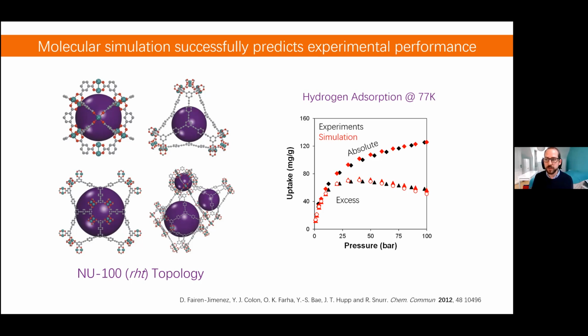Sometimes when we have such good simulations, we say, well, be careful. Did we do everything correctly? We are not always expecting to have such a beautiful overlap. But what is important is that the simulation is not a fitting of the experimental data. There is no numerical approach here trying to fit the experimental data. We are running the simulations just with the information that we take from X-ray diffraction. We have the structure of this NU-100 and different materials, and then we start running the hydrogen simulations, and we try to understand if we are able to predict this correctly. So we are validating the simulation approach.